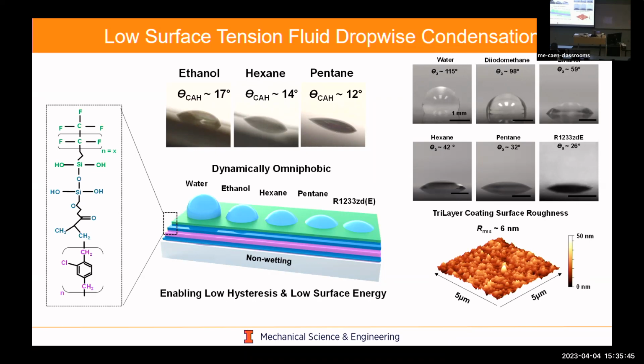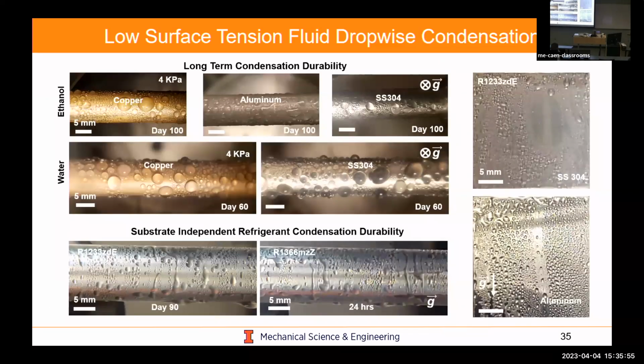And so these are more pictures of advancing and receding contact angles. The 1233 ZDE has a finite contact angle, but it has a very small hysteresis, which I'll show you in a second. And so if we look at low surface tension condensation, of course, ethanol works great. This is exciting. Water, we expected this. The interesting part is we could actually get stable dropwise condensation of this ZDE and also this 1336 MZZ, which we were very excited about.